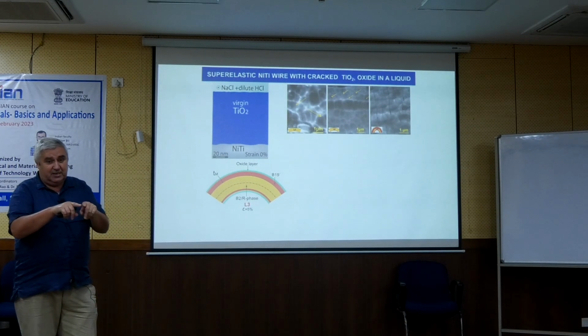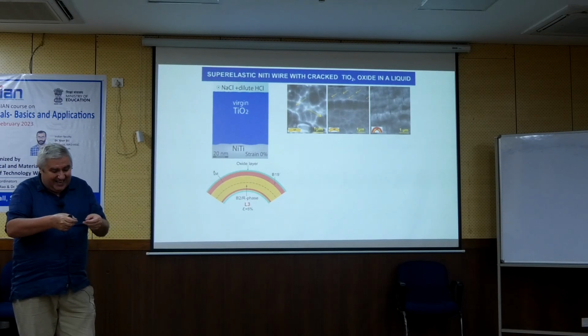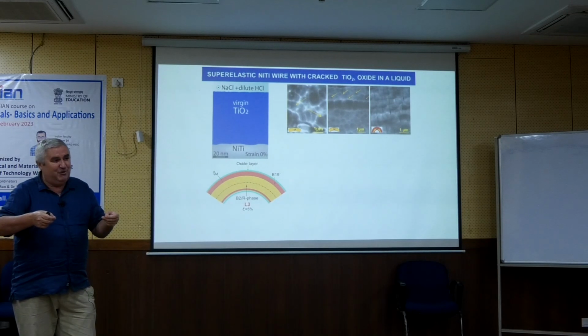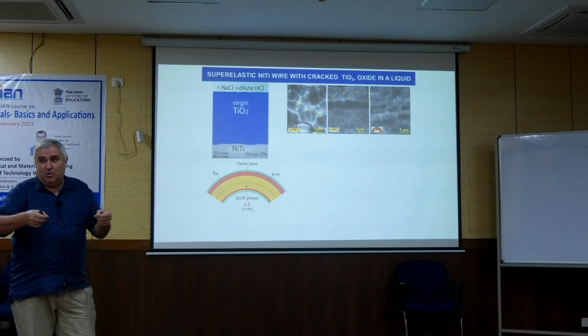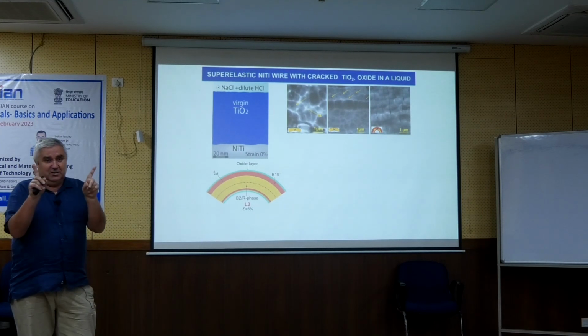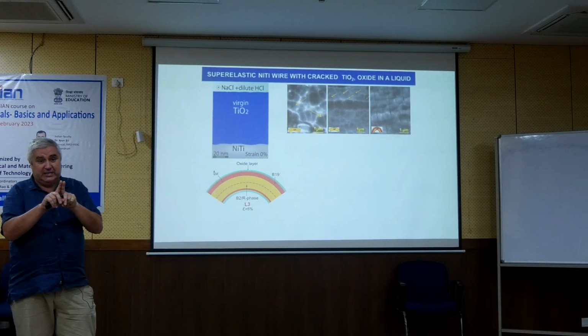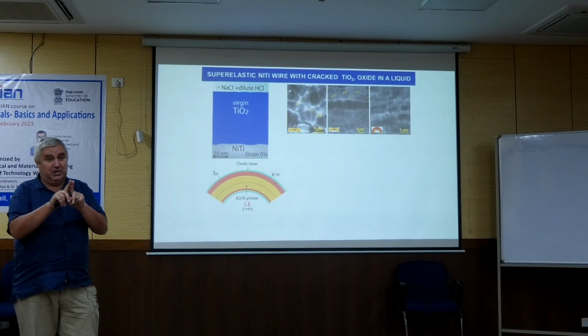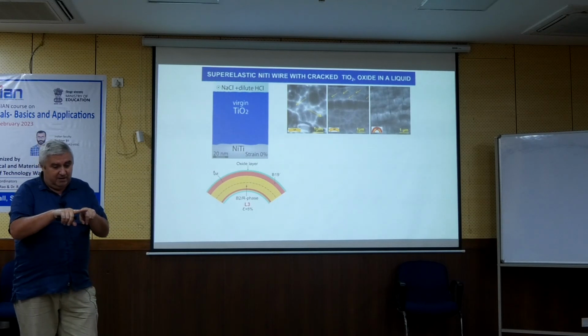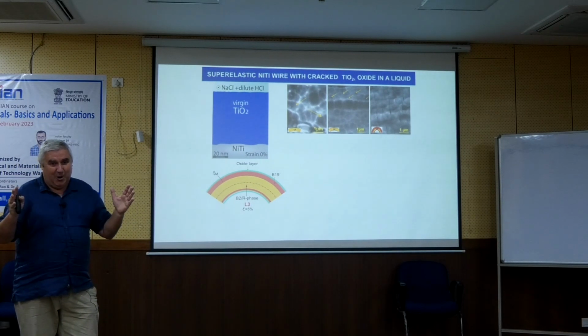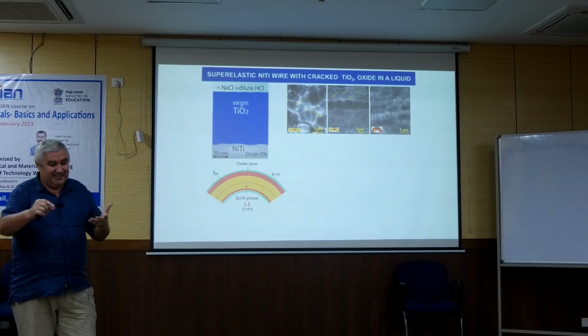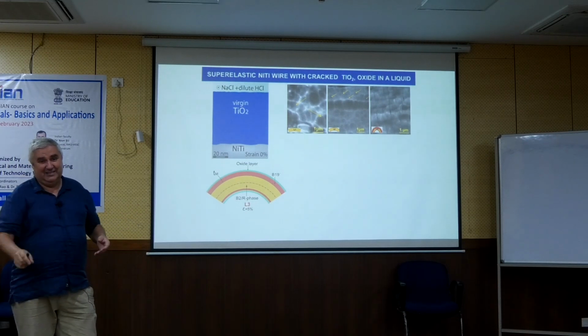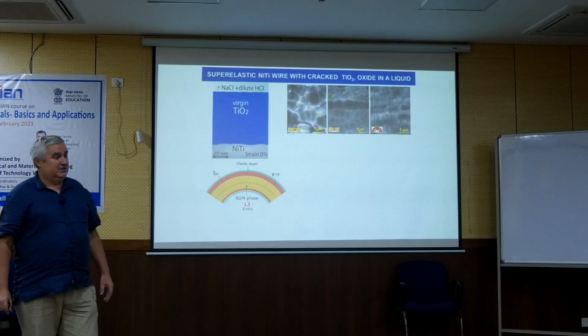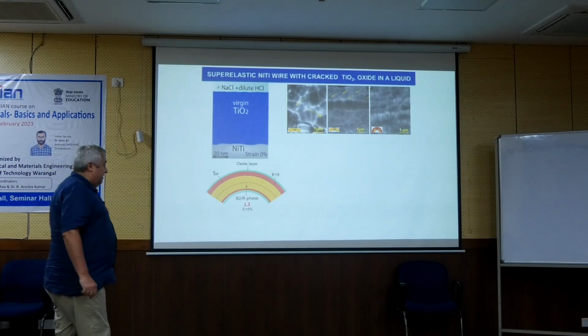It's even such that you can see the cracks in the oxide only if you look on the nitinol under stress, because when you unload, the cracks will close, and you will not see them. Even the SEM doesn't have such a good resolution, it will be very, very tiny. But when you stretch it, the cracks will open, and suddenly you see there is a 1 micrometer black track of the crack.